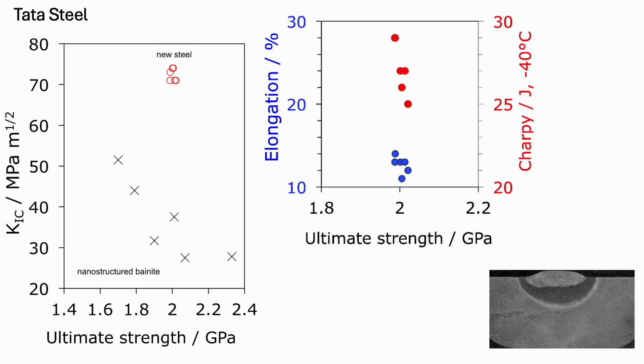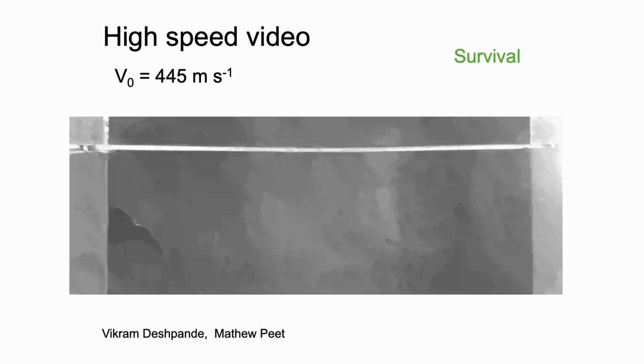So here, for example, you can see that the new steel has a toughness of 75 megapascals root meters and even a Charpy toughness at minus 40 degrees centigrade, okay, and at a strength level of about 2 gigapascals. And it can be welded as well. So I'll show you one particular application.